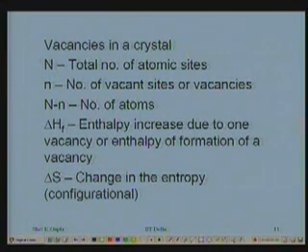Let us consider capital N as the total number of atomic sites in the crystal. Out of this total number N, let small n be the number of vacant locations, or the vacancies. So I have total capital N minus small n atoms in my system, and small n is the number of vacancies. We will show that small n is much, much smaller than capital N usually. And I showed you that the bond lengths will usually increase near about in that region, and therefore the bond energies go up and the enthalpy of the crystal increases because of one vacancy.